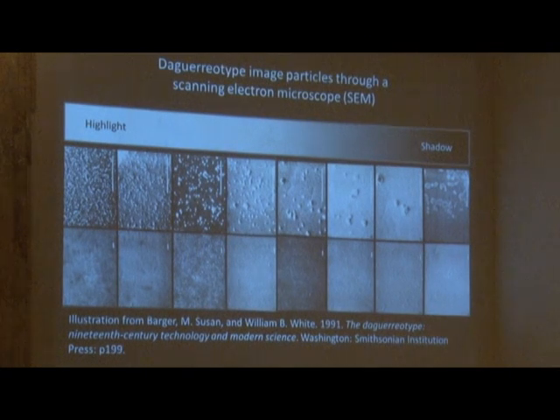Whereas when you step down, or up, to shadows, the image particles get bigger and bigger and kind of odd shaped. And by the time you get to shadow, they're kind of rocky shapes, and the distribution is kind of irregular. They're clumps, and then there's a big area of nothing. The morphology and distribution of these superfine image particles interact with light in a very specific way that creates unique light reflectance, and that makes daguerreotype images.